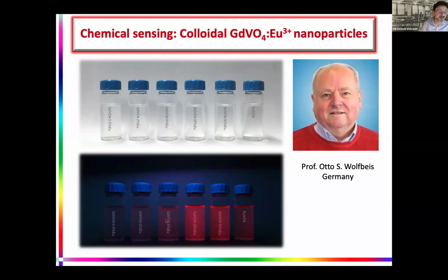And we did this research many years ago under his supervision, using nanoparticles to sense chemical analytes. It was a well-known field, but mostly semiconducting quantum dots were used at that time. And we developed gadolinium vanadate nanoparticles, which were only a few nanometers in size, and they are not cross-sensitive to the environment. They are only sensitive to hydrogen peroxide. They quench the emission under hydrogen peroxide. And when he saw our results, he offered his help to guide us to start this field. And I will show you why this field is so important.